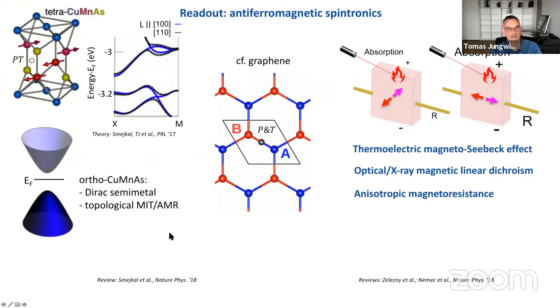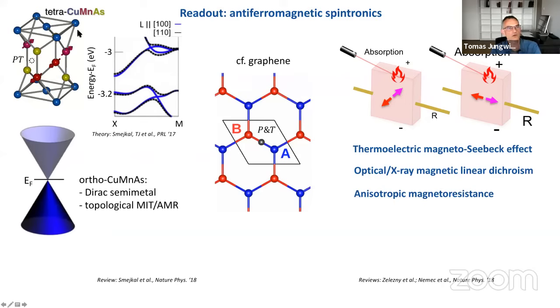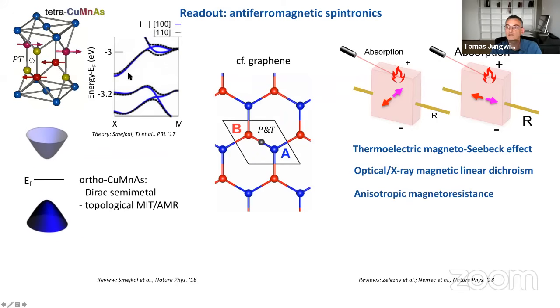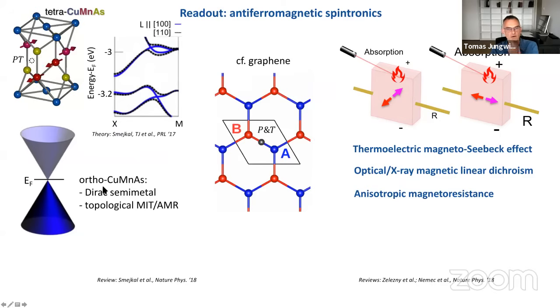But an important caveat to make here is that for this to happen, you have to have these Dirac points, these topological features, at or very close to the Fermi level, and no other trivial bands crossing the Fermi level. Now, if we look at our workhorse tetragonal copper manganese arsenide, it has these Dirac crossings, and you can close and open the gap by changing the direction of the Néel vector. But what you see is that these features are buried deep in the Fermi sea, so they are not going to affect strongly our magnetotransport property. There's a theoretical prediction, which is yet to be verified experimentally, that there are other antiferromagnetic systems which might have the Dirac point right at the Fermi level and no other bands crossing. And an example could be the orthorhombic phase of copper manganese arsenide.